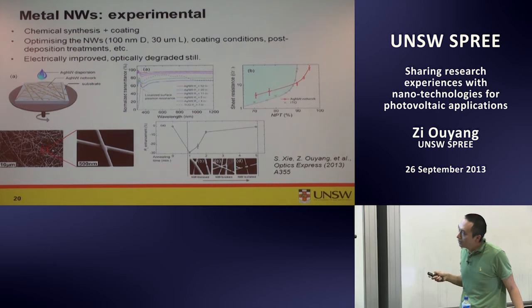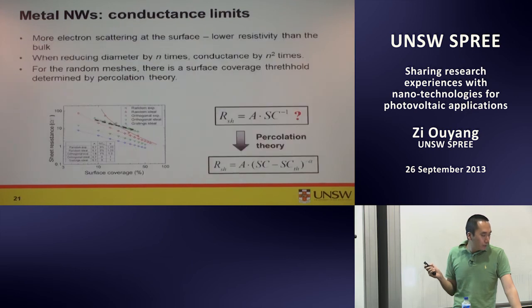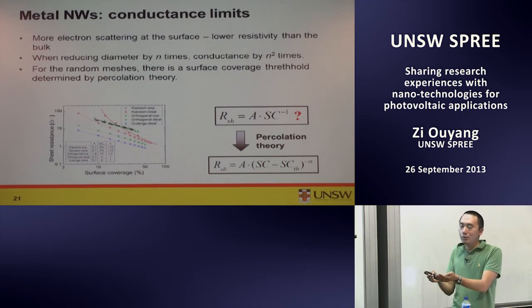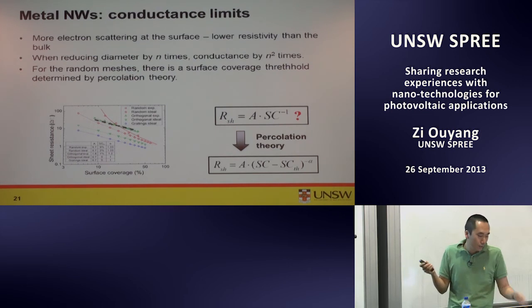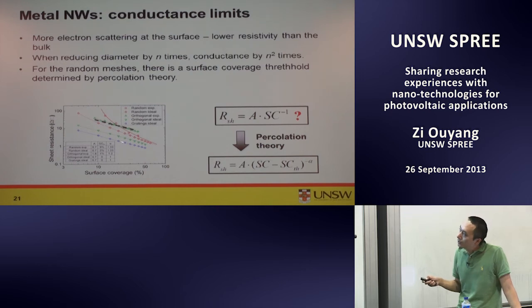And when we keep on annealing it, we see the nanowires actually broke, and we get back to normal again. It's basically not conductive in a large scale anymore. So yeah, this is the idea. Then we think about what's the limit for conductance. So we assume we have no contact resistance actually between the nanowires and between the nanowires and the silicon or whatever material. And we predict the curve, ideal curve, experimental curve.